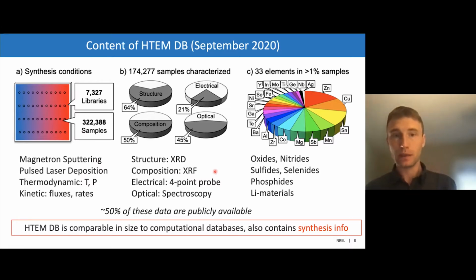For approximately half of all of this information, we have some ways in which the sample libraries have been characterized by measuring their composition, structure, electrical and optical properties, as reported in the public version of the database. So we measure structure by X-ray diffraction, composition often by X-ray fluorescence, also other techniques, but X-ray fluorescence data is what's reported in the database. Electrical properties by four-point probe methods, and optical properties by UV-vis transmission and reflection spectroscopy. And approximately half of all of this data are publicly available.